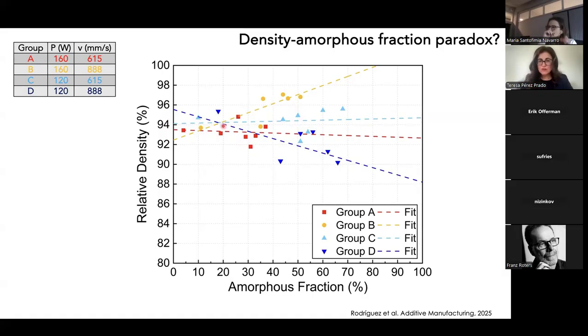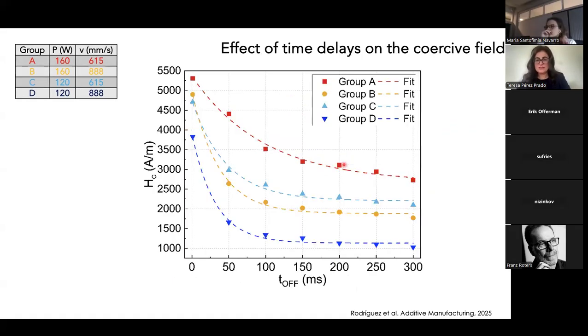In these two other conditions, light blue, group C, group A, we can increase the amorphous fraction without at least losing or reducing significantly the density. So it does look like time delays help. But if you take a look at this data, you can see that the highest amorphous fraction that we obtained using these commercial alloys, even with the introduction of time delays, was about 70%. So still we are very, very far from our target.